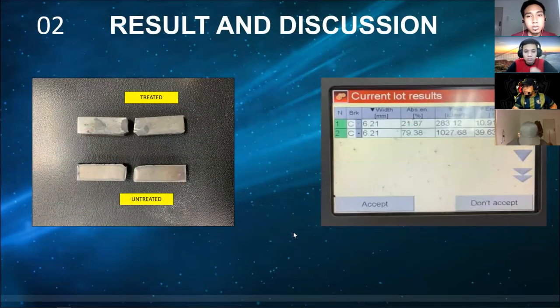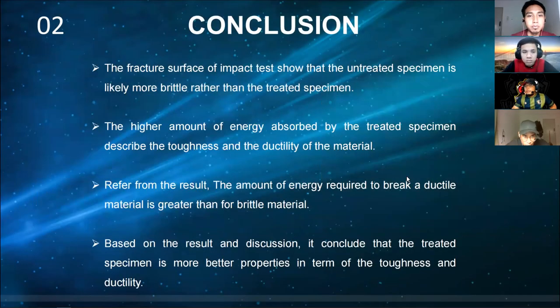Next, this is the result of the test, which is, as you can see, there is the picture for the treated specimen and untreated specimen. The Charpy result for the treated specimen is 39.632 joules and the untreated is 10.918. So for the conclusion of this impact test, the fracture surface of the impact test shows the untreated specimen is slightly more brittle than the treated specimen.